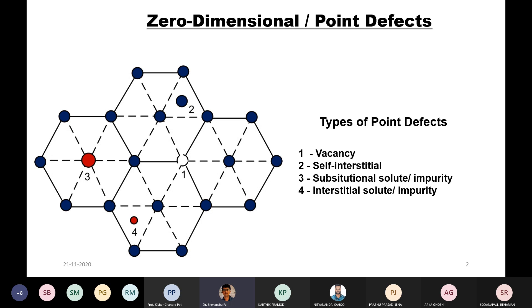Above zero Kelvin — the absolute zero temperature — a vacancy-free material is physically impossible, because vacancies are an equilibrium kind of defect that helps the material become thermodynamically stable. In a covalent solid — for example, a semiconductor — the situation is more involved. Both self-interstitials and vacancies can be dominant intrinsic defects at equilibrium for such semiconductor materials. The different point defects — vacancy, self-interstitial, interstitial, and anti-site — are very important when learning about atomic-scale diffusion mechanisms.